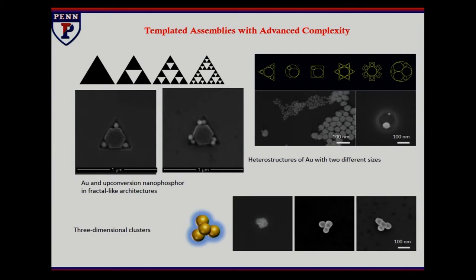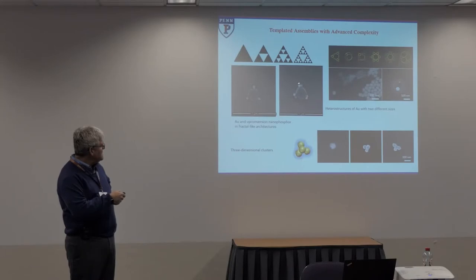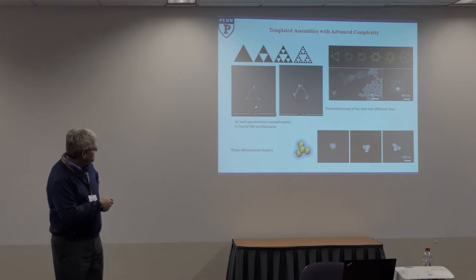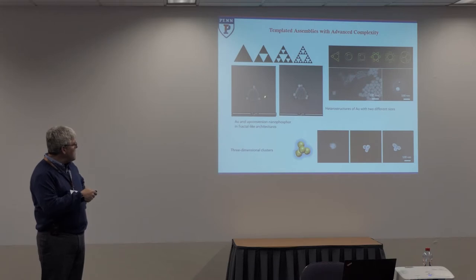One of the things that we had some fun with was this idea of using, again, a sort of lock and key. If you make template structures that will trap particles of specific geometries, but then leave a little bit of extra space available, you can fill those with one particle if the space is sized so that only one extra particle can fit, or in this case, by putting in slightly smaller particles or etching a little bit more to make a larger hole, you can have room to have groupings of particles.